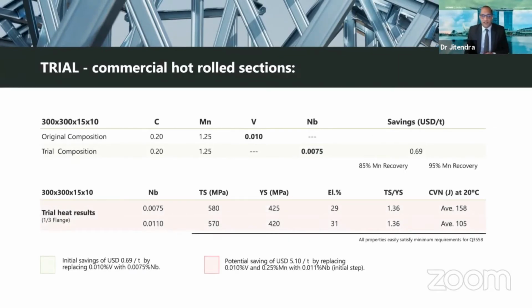And this is an example of another commercial trial that was done with a client of ours in China. In particular, we managed to go down to 75 ppm niobium compared to their 100 ppm vanadium composition. So they were already using very low vanadium levels. We were able to look at getting rid of the vanadium and adding even lower niobium levels because of the potency of niobium. In this particular case, again, we were able to save about 70 cents a ton. Because they're making over a million tons of this type of commodity product, the savings there are quite apparent.